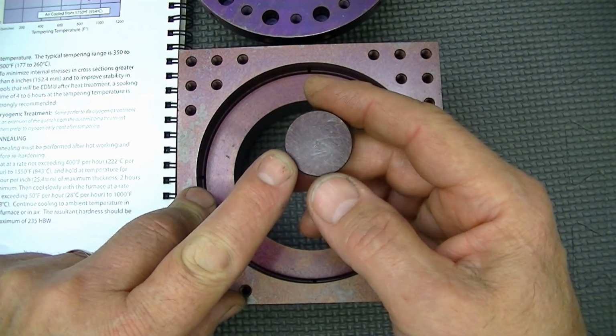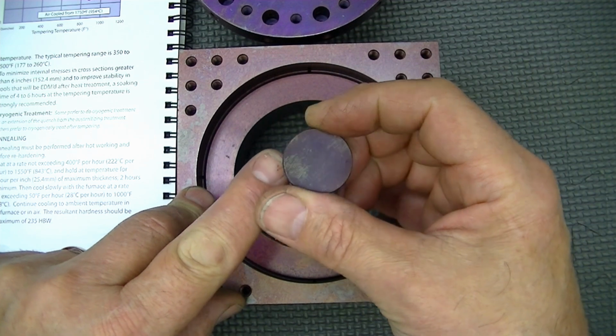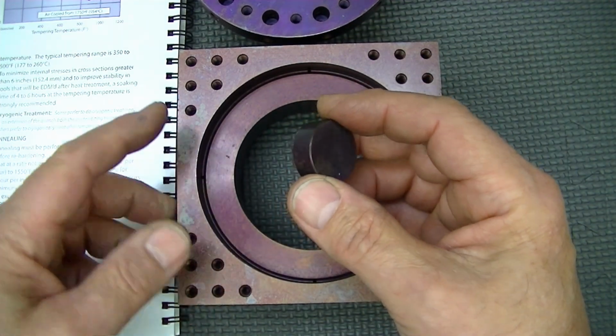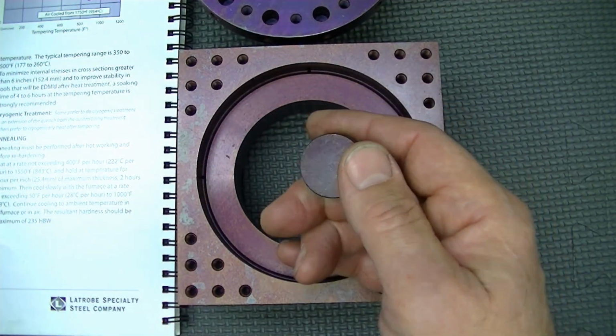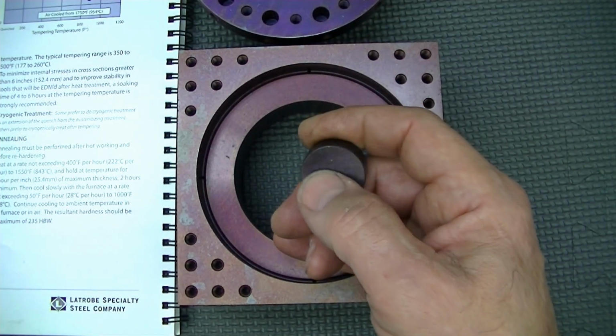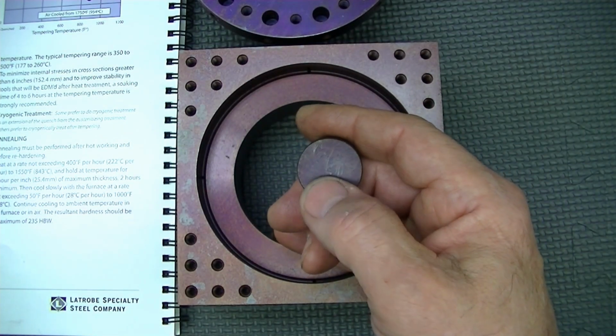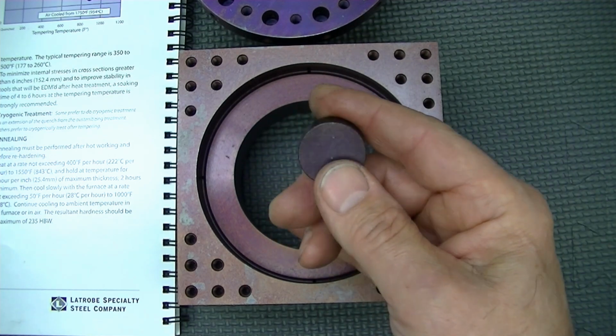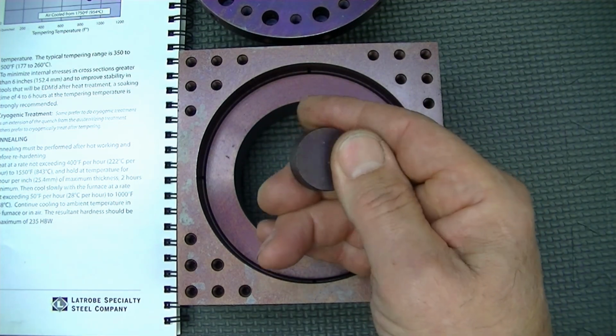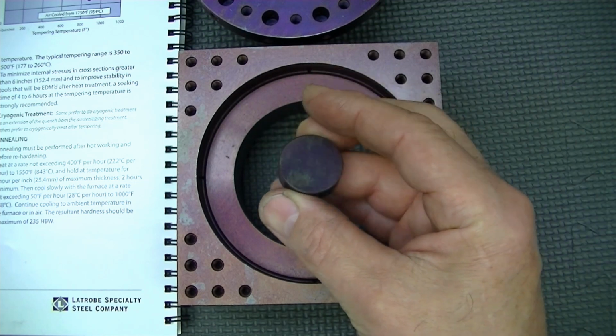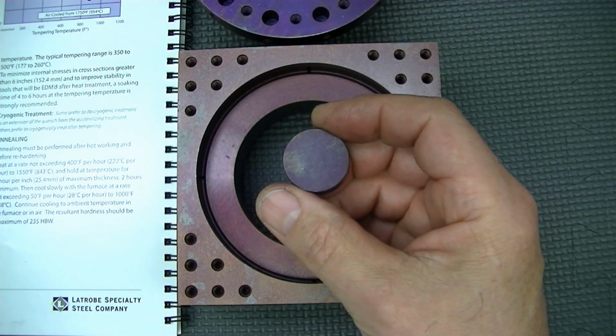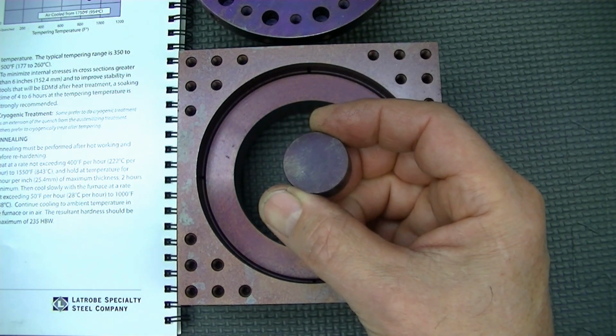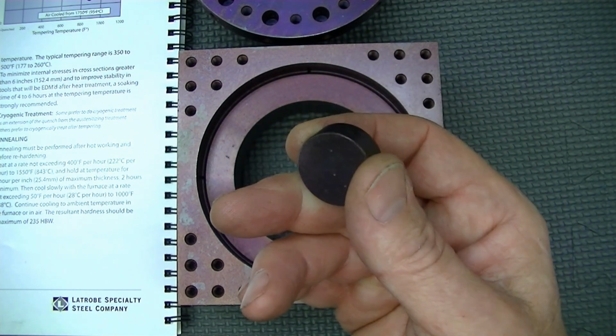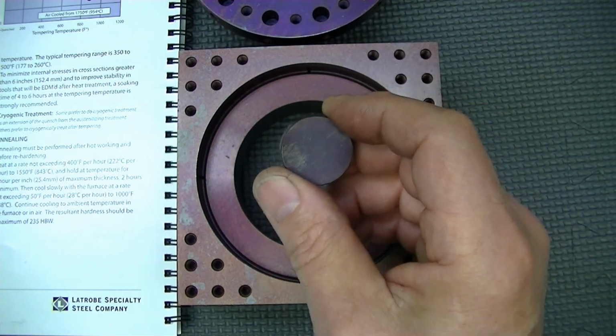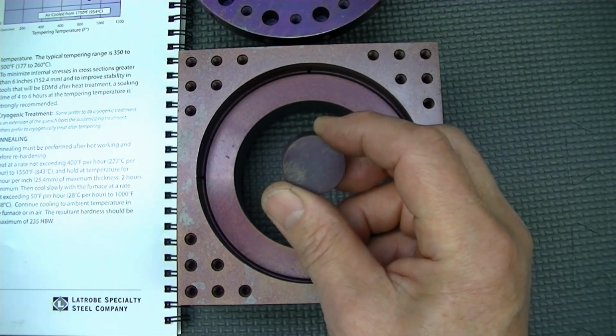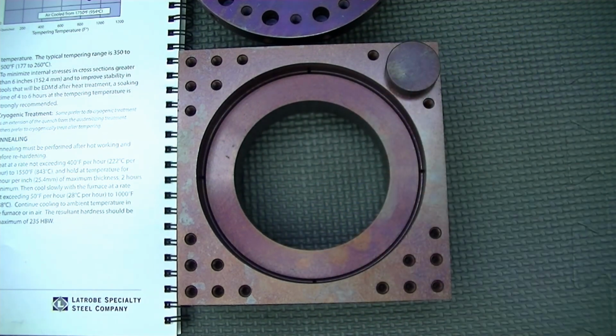So a piece of the same material. I don't typically worry about it being the exact same material, like from the exact same bar. If it's A2, it's A2. I'm not typically worried about super precise Rockwell values, so I don't worry about it. But you send a piece along, make sure it's got smooth, flat surfaces, because that can influence the hardness reading if you don't have a good bearing on the anvils when you're testing. So good tip, send test pucks, put it on the order. Do not test parts, test puck only, and you're good to go.